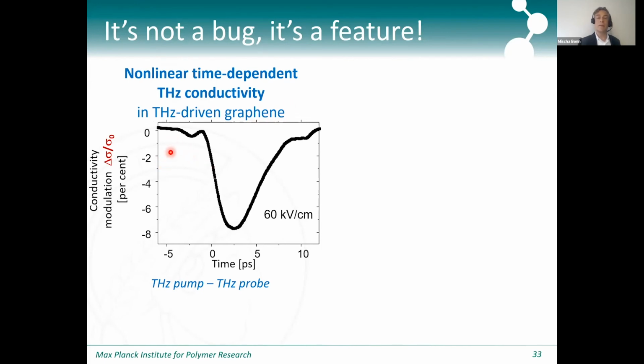And so here is an illustration of how nonlinear it really is. This is a terahertz pump, terahertz probe measurement. Again, you have to keep in mind, this is one monolayer of material, and you can change the conductivity or the absorptivity of that material by almost 10% with a fairly moderate field. Here you see that the conductivity drops dramatically. This is averaged over the whole terahertz spectrum by 10%, and it recovers again within a few picoseconds. You also see that it goes back to roughly the original state it had before the terahertz pump pulse hit the sample.